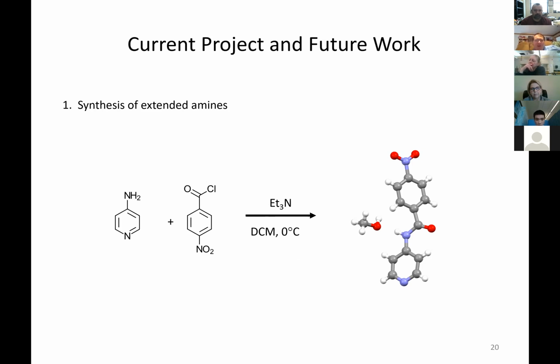We've got to keep it cool because it's one of those very highly exothermic reactions. I tried it at room temperature just to prove it, and man, literally it will foam and bubble right out of your container and you lose almost everything. So you cool it down, just ice water is pretty much good, and everything stays magically inside of your beaker. You don't make a mess for your lab coordinator to clean up.